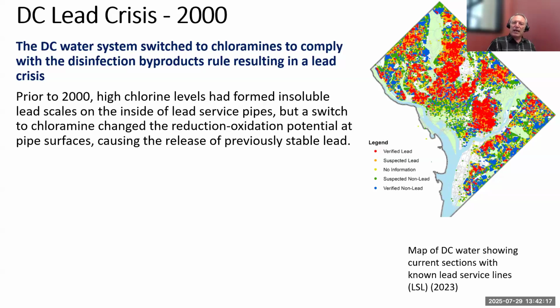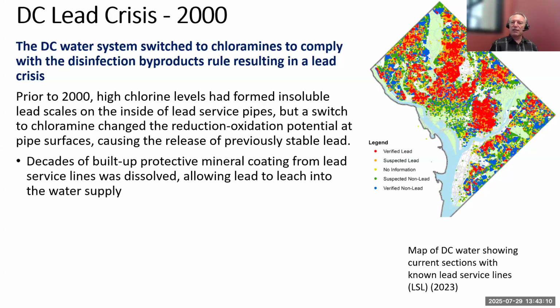So, but prior to that, they had been using chlorine for a long time, and they had this long period of time during which they accumulated a scale in the inside of the pipes that had lead inside the scale. It was retained, it was safe, it wasn't going anywhere, and it was a lot to do with chlorine. The chlorine there that was being used, fairly high chlorine levels, helped to form these scales on the insides of the service pipes. When they switched to chloramines, it changed the oxidation reduction potential at the pipe surfaces, and this previously stable lead scale was now dissolved and was released. So they had decades of this built up mineral coating in the service lines, and then it was dissolved and lead was allowed to leach into the water supply.